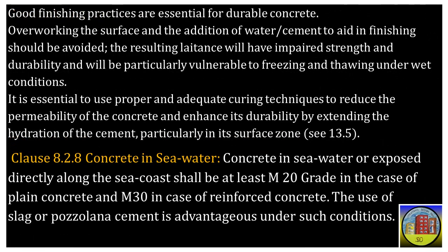In clause 8.2.7, titled Compaction, Finishing, and Curing, emphasis is placed on the significance of good finishing practices for ensuring durable concrete. It's advised to refrain from overworking the surface or adding excess water or cement during finishing, as this can result in weakened strength and durability, especially vulnerable to freezing and thawing in wet conditions due to the formation of laitance. Furthermore, proper and adequate curing techniques are highlighted as essential for reducing concrete permeability and enhancing durability. Effective curing extends the hydration of the cement, particularly crucial for the surface zone of the concrete, refer to clause 13.5, to ensure optimal strength and durability.